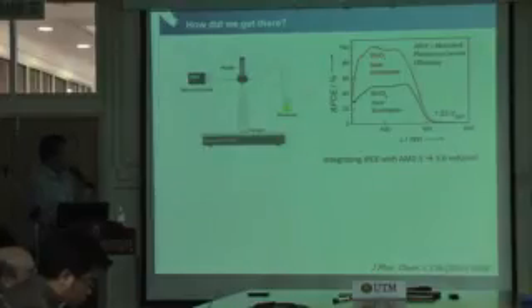Now if you integrate this, multiplying it with AM1.5, the solar spectrum, you can predict how much photocurrent you will actually get if you illuminate this with sunlight. And it turns out to be 3.6 milliamps per square centimeter at that point. But then we measure it under a solar simulator, AM1.5 illumination, and we observe only about 0.5 milliamps per square centimeter. So these discrepancies, we then try to analyze.